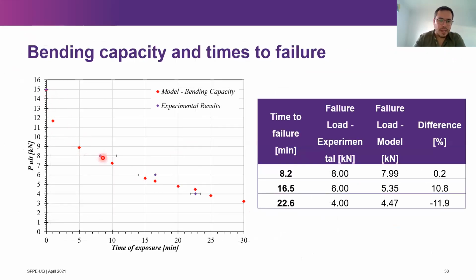We also compare the experimental results in the bending capacity, or what many people understand as the fire resistance, right? So you see that for 8 kilonewton, the time to failure was around 8 minutes. For 6 kilonewton, the time to failure was around 16.5 minutes. And for 4 kilonewton, the time to failure was around 22 minutes. With our model, we predicted that reduction in the load bearing capacity. And we observed that the variation between the experimental results and the numerical model was around 11% difference.